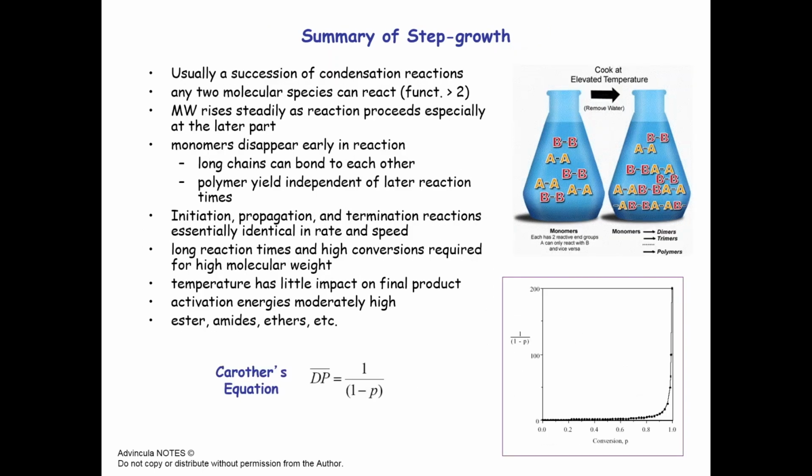Now, the second major type of mechanism is based on step growth. In step growth reactions, you have monomers that react early, and therefore all the monomers are consumed very early on to form dimers, trimers, and tetramers. You really do not see a high molecular weight at the beginning, but only at the end of the reaction. In fact, a very important requirement is that the reaction should be a high yielding or high conversion reaction in organic chemistry, such as esterification, amidation, and so on.